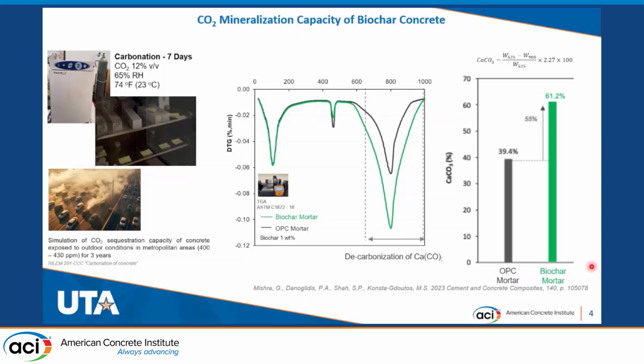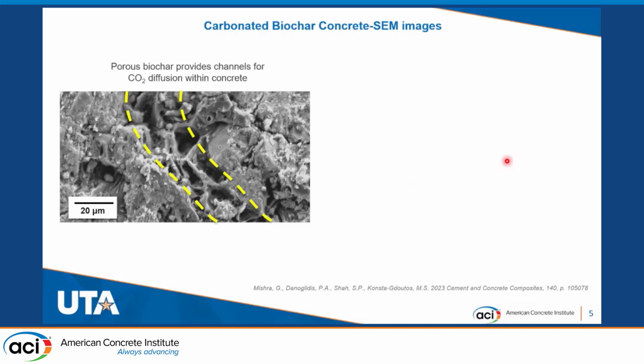And as we observe from the graph in the right part of this slide, the carbonated biochar concrete specimens exhibit an almost 55% higher CO2 mineralization capacity compared to the OPC mortars. This behavior can be attributed partly to the porous microstructure of biochar.